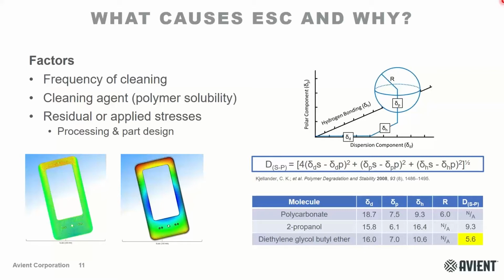So we did a little exercise with polycarbonate and took a few common ingredients you might find in disinfectants, such as 2-propanol and diethylene glycol ether. What we can see is that 2-propanol falls just outside of the radius of the solubility sphere for polycarbonate, the distance being 9.3, whereas the radius is 6. For diethylene glycol ether, the distance was calculated to be 5.6, so it actually falls inside the solubility sphere. So what you might be able to conclude from this is that if there was a damaging component that would solvate or at least swell the polymer here, it could be the diethylene glycol ether. This is something to consider, and we'll talk a little bit more in the upcoming slides about how solvents influence the overall mechanism.